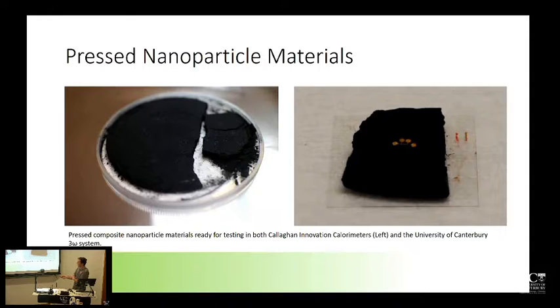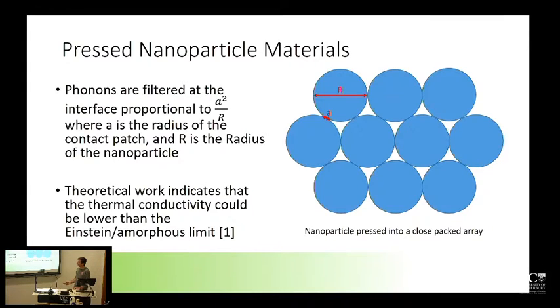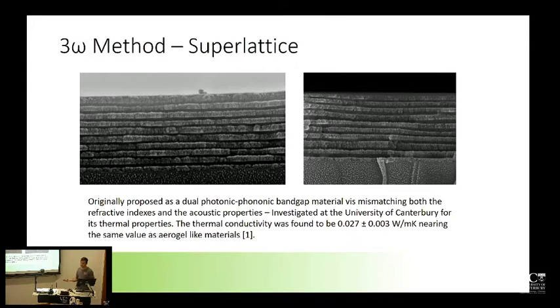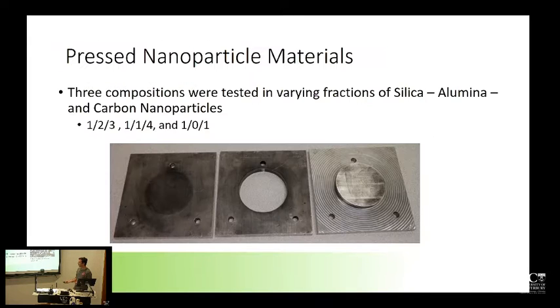Yeah, so these were the materials that I ended up with, and I had 3 different types of compositions. They were 1 part silica to 1 part alumina to 4 parts carbon by weight, and then in the same order 1, 2, 3, and then a 1, 0, 1 type composition. And these were 3 compositions which had a precedent in the literature, and according to the literature at least, they had a thermal conductivity of 6 milliwatts per meter Kelvin. So 1/4 that of the superlattice that I originally measured. So it seemed like a promising direction to go in, and that's what we went with.